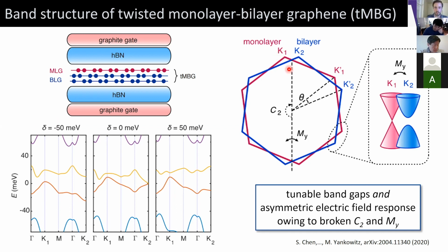One edge of this valley, the K valley, is a monolayer-like dispersion, and the other is a bilayer-like dispersion. So when we switch these, we get something different. So this symmetry is now also broken, whereas it is not natively in twisted double bilayer graphene, which would be the same by switching the bilayer graphene on the top and bottom. So reducing the symmetry again gives us yet more experimental knobs we can use to tune the correlated states in the system. We can tune it with both electric field and the sign of the electric field.